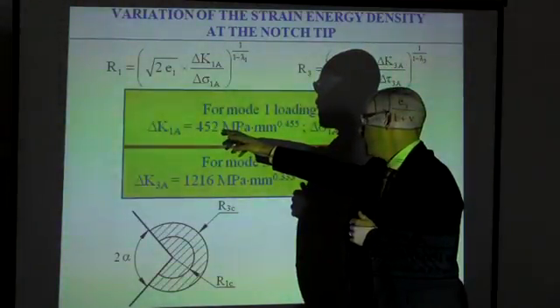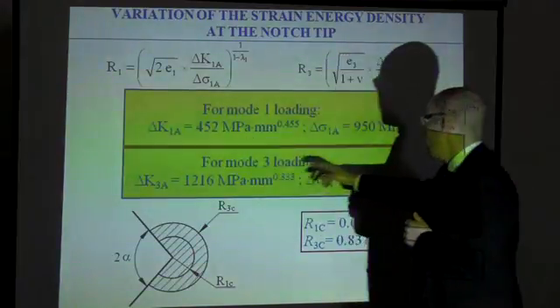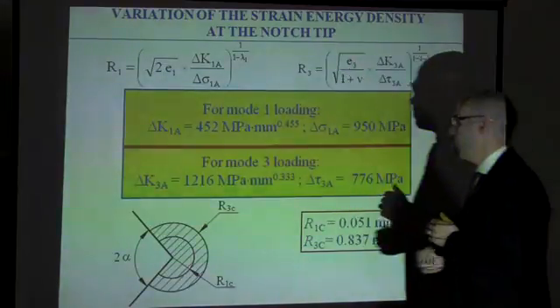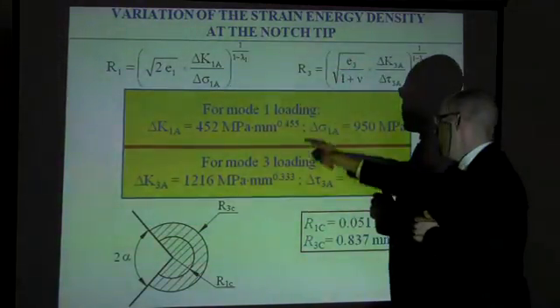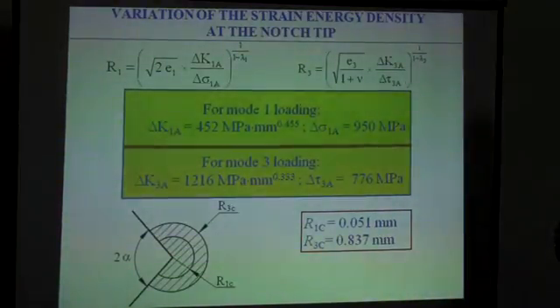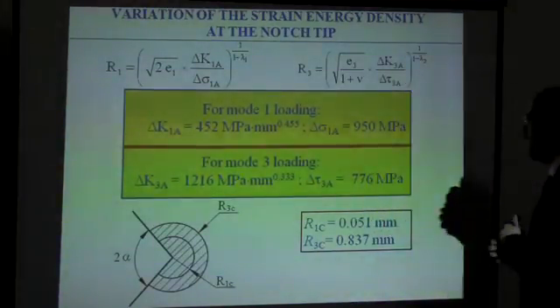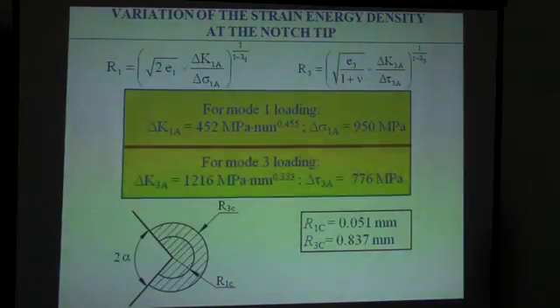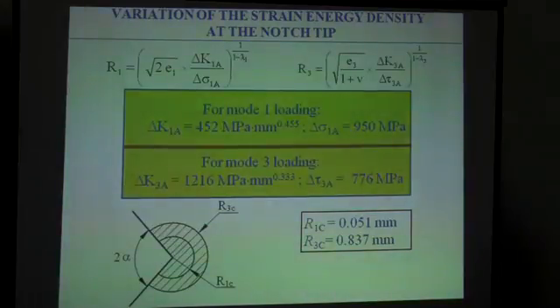These critical radii are linked to the critical stress intensity factor under mode 1 and mode 3 loading, and this information is derived directly from sharp notches. And this information is the stress range of plain specimens, so this information comes from unnotched specimens. As we always do when applying the strain energy density, we compare the strain energy density of very severe notches and, on the other hand, the strain energy density of a plain specimen. To evaluate the critical radius, we have to equate the two equations, which come from two pieces of information: the information from sharp notches and the information from unnotched material.